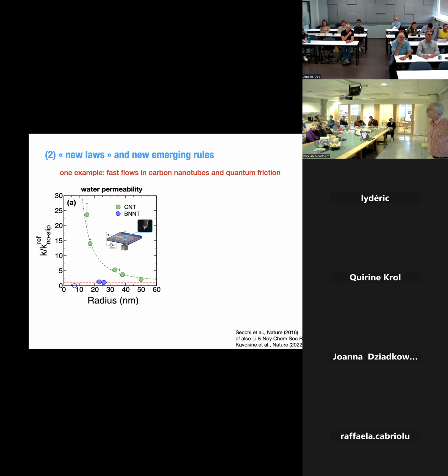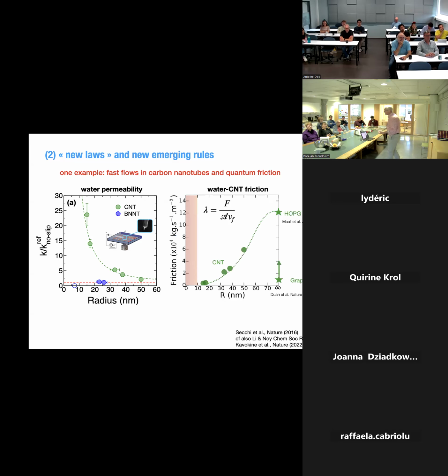And you see, carbon is very special. And boron nitride actually obeys the Poiseuille law. Boron nitride is interesting because it has exactly the same structure as carbon, except boron nitride is insulating, and carbon, you know, is semi-metallic. So that was extremely weird, especially that it occurred in quite large radius. You see, 20 nanometers. So that was very strange. And actually, if you translate it into friction, so that's really a measurement of the friction of water on the surface, the friction coefficient decays with the radius. Of course, we would love to go to 0. That would be superfluidity. Of course, it will not. But at least you have a strong decrease.